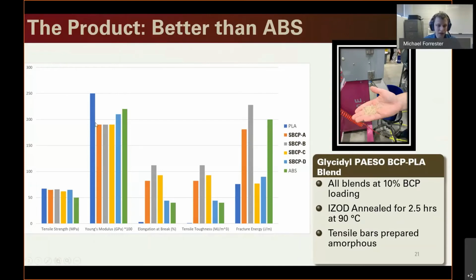We do see a slight decrease in the stiffness of the material, but what's really impressive is our elongation at break and our tensile toughness and our fracture energy. This material has arguably much better mechanical properties than even ABS, and it comes from a resin that is bio-based and biocompostable, and is a lot more affordable.